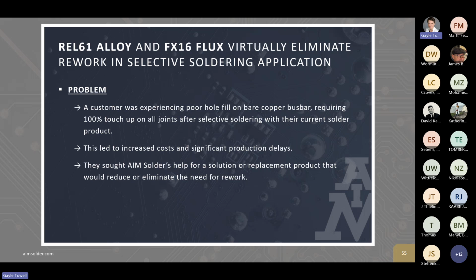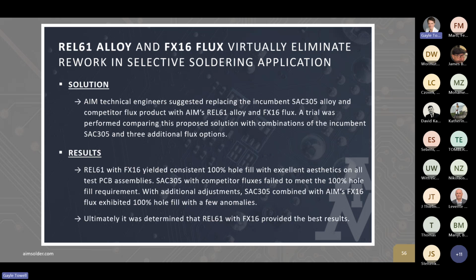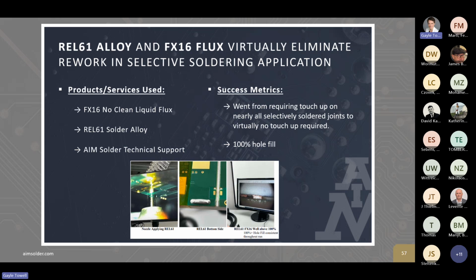And so they tried out the combination of our FX16 liquid flux and the REL61 alloy. And the end result was consistent 100% hole fill, excellent aesthetics on the boards, and almost no rework required in the end. So they went from needing to touch up nearly every single joint to almost no touch up required, which was a huge difference for this customer.